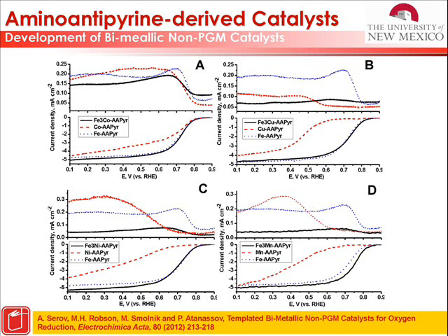And then at the end we said, let's make a catalyst like we make cement, with species that do not even dissolve. So we took this charge transfer salt, which has a traditional name, nicarbazine. The IUPAC name is unpronounceable. This is this thing together, with a dot here. The dot is missing right now. I don't know where the dot is, but that's okay. So this is the charge transfer salt. It's a conductive organic salt. This is not soluble in anything. This is a black powder, not soluble in anything.